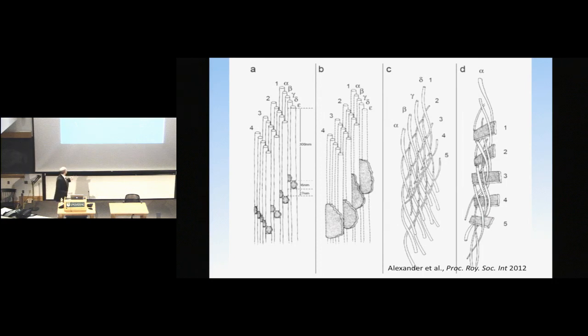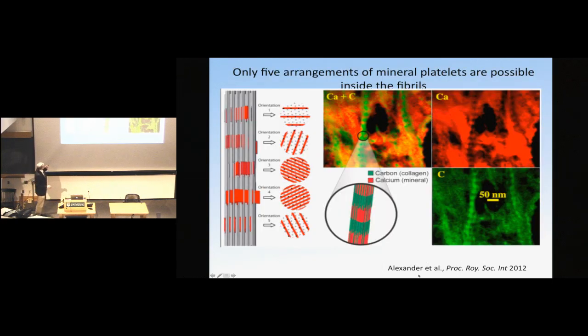These early studies, for those in the field, this is the Hodge-Petruska model. There was just no attempt to do the simple steric calculation of how much mineral is accounted for. And even in these studies, it's a stretch to account for all the mineral. So what we come up with, from this slide, is that although there are 5 possible orientations for mineral platelets inside these collagen structures, if we take the densest possible orientation of these platelets being pushed through these rods, so one in every 5 rods is discontinuous at each one of these gaps, then we end up with a maximum volume fraction of 21% mineral.